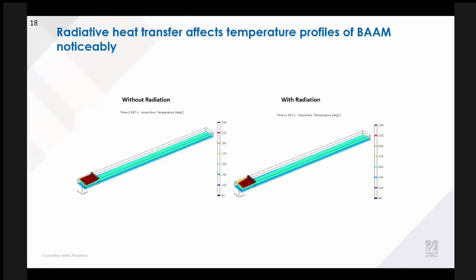Another thing that we observe is that radiation is super important in BAM. If we don't account for radiation, our simulation predicts much hotter samples, and then we've got these much longer tails as we print. And so radiation is a very important heat transfer mechanism. And there's been some other work in the literature that suggests that radiation accounts for about 30% of heat transfer in BAM. And so that's consistent there.